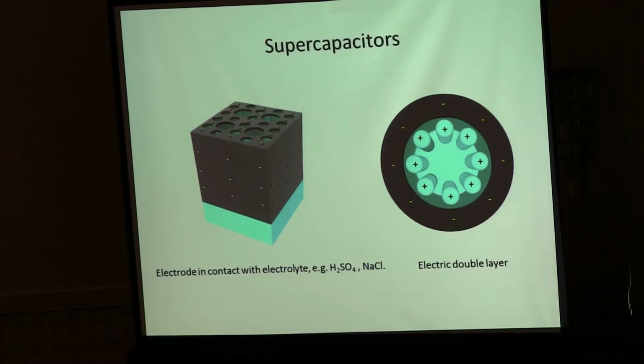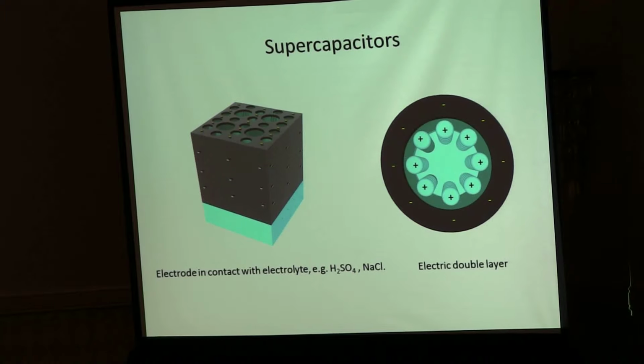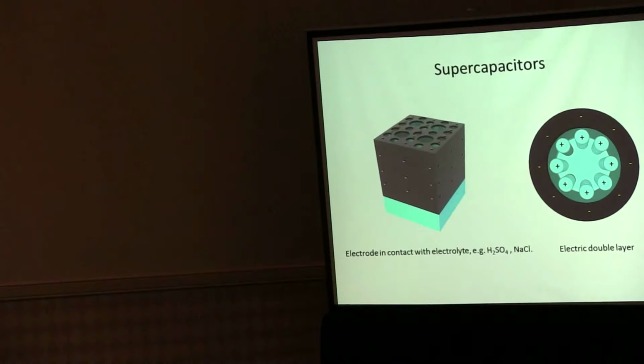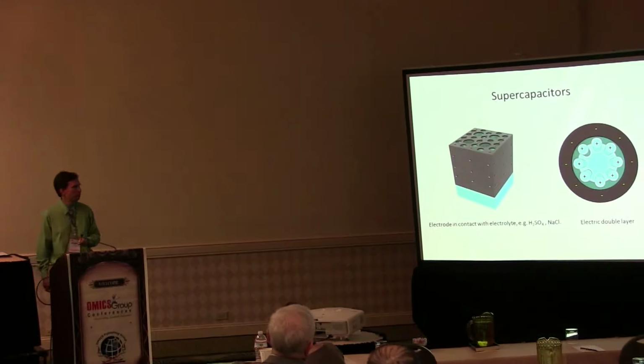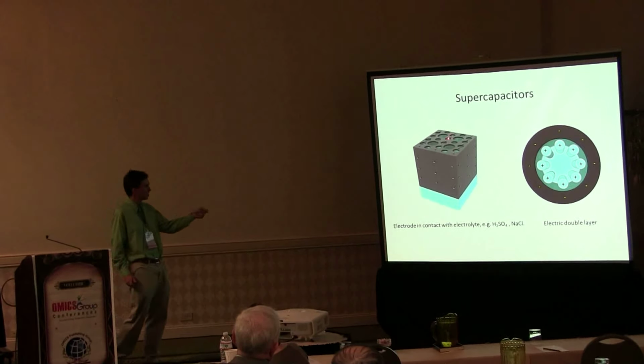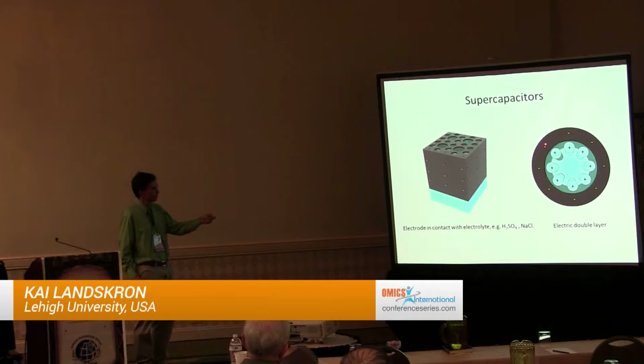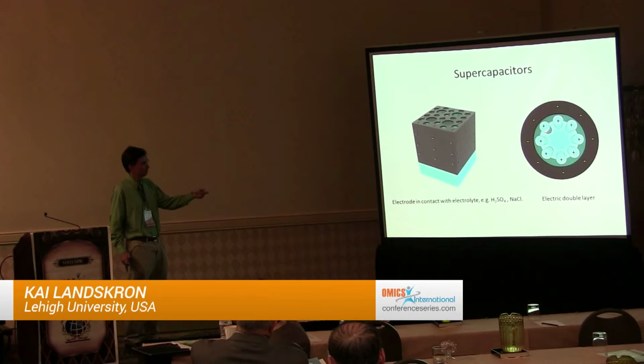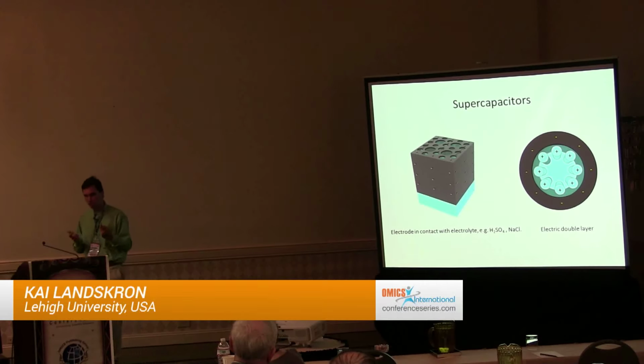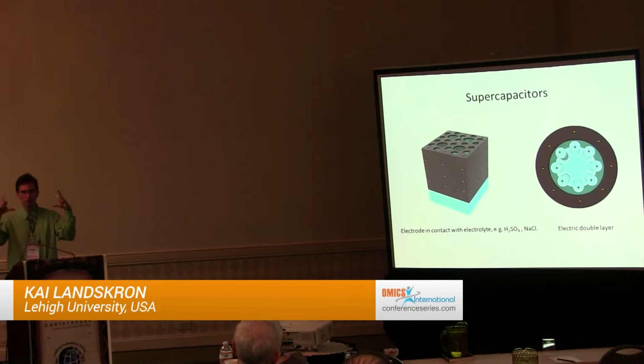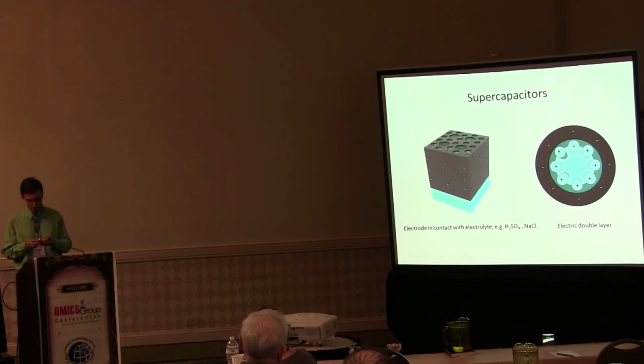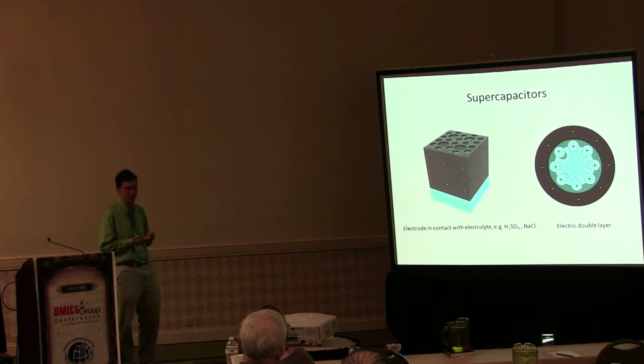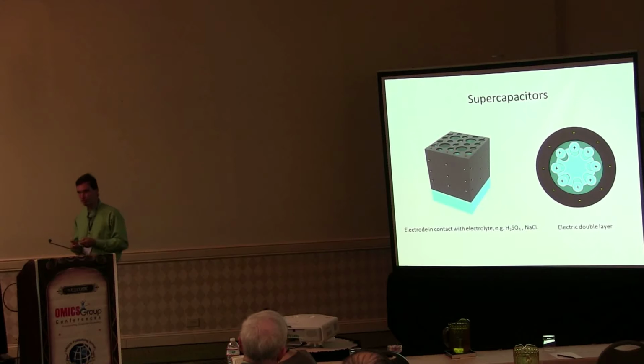And you can do this when you switch from a parallel plate capacitor to a supercapacitor. In a supercapacitor, your electrode material is in contact with an electrolyte that contains ions. So when you charge your capacitor, each electron that you inject is counterbalanced on the porous surface by a counter ion that comes from the electrolyte. And for that reason, you form a so-called electric double layer on your porous surface that leads to much higher capacitances and to a much greater number of electrons that you can introduce.